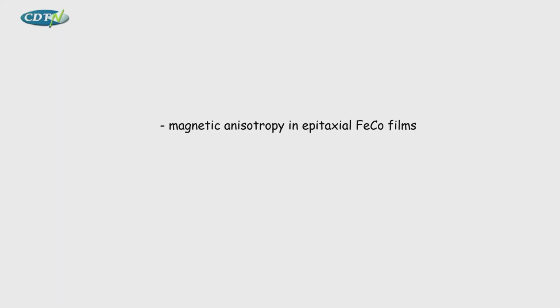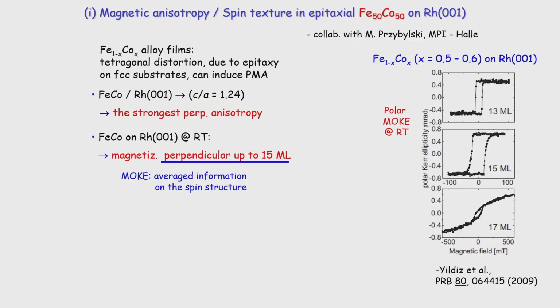Okay. A few words about magnetic anisotropy. One way to get perpendicular anisotropy, for example, iron cobalt is a very important material for perpendicular magnetic anisotropy. And the way to do that is to get tetragonal distortion by growing epitaxially on different substrates. And this is a model system, iron cobalt on rhodium. You have a big distortion, a c over a of 1.24.